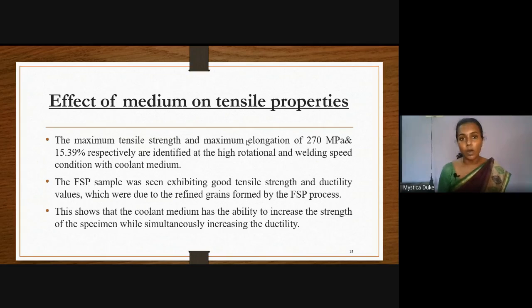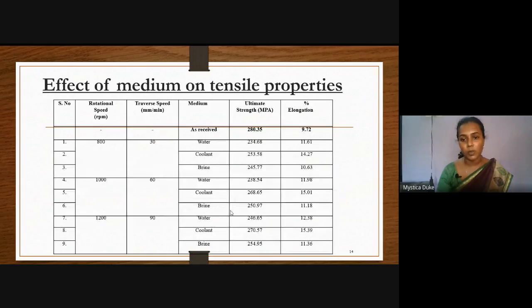Actually, the cooling oil produced better and maximum elongation and maximum ultimate strength. You can see it here. At the high parameter combination, the coolant oil produced maximum ultimate strength and maximum elongation. This, as I mentioned before, is because the coolant oil takes away more heat, thereby reducing the size of the heat affected zone and also refining the grains further and better than any other medium here. So the tensile properties tend to be better with cooling oil.